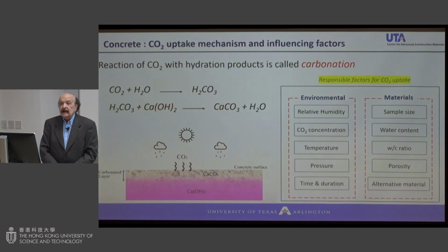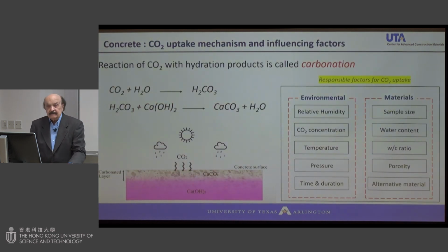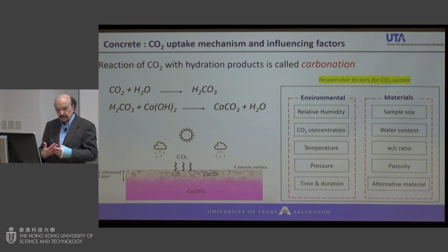So what is the breathing mechanism? If you look at the surface of the concrete, you have CO2 in the atmosphere, and that CO2 combines with water to give carbonic acid, and that combining with calcium hydroxide gives us calcium carbonate. And calcium carbonate is what we talk about as carbonation.